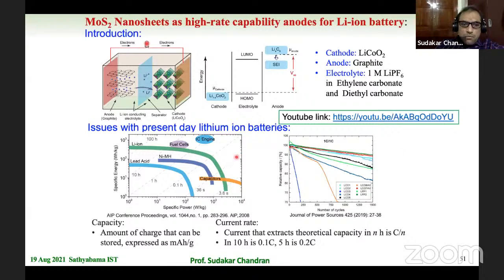structures. The challenge is, the lithium-ion batteries work very well, for example, right now on my computer, because I require very small power, and as long as I draw very small power, it can deliver maximum specific energy. But if I need to draw a large power, if I want large specific power, the amount of energy that I can get out of the battery drastically goes down. Which means I cannot use these batteries in vehicles. If I want to start the vehicle, I need to draw a large power, and that's not possible. Therefore the batteries literally fail. And therefore the challenge now is to make batteries which can deliver a large specific power and so on.